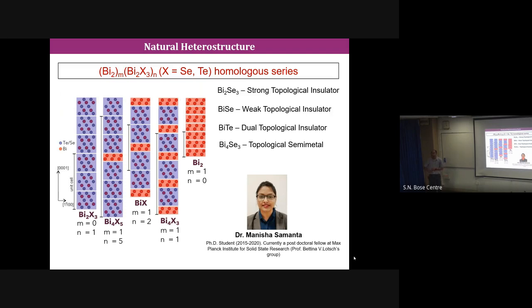So by changing the structure, you get a dual topological insulator, which means you basically have a weak topological insulator as well as a topological crystalline insulator. Yeah, so it is a mixture of weak topological insulator, because some of the surface states are protected by time reversal symmetry, and the other part of the surface states are protected by mirror symmetry. That is the topological crystalline phase. So both phases coexist in it.